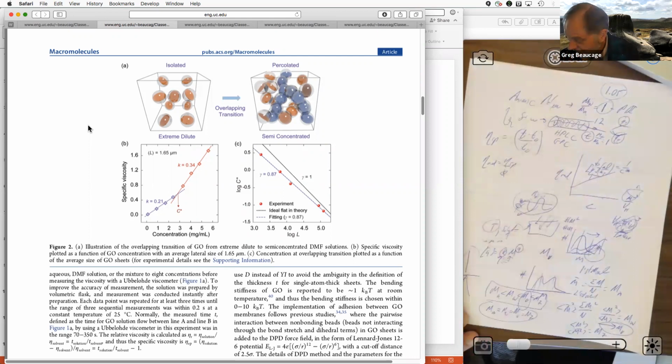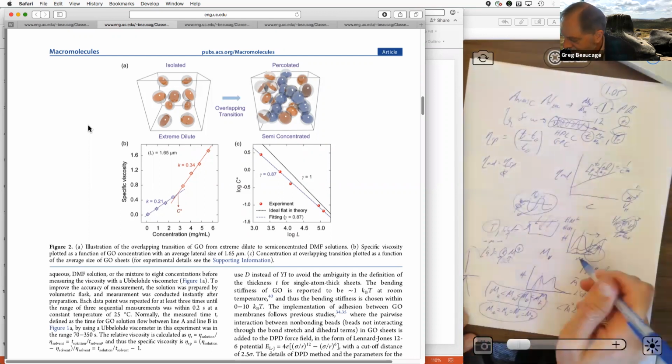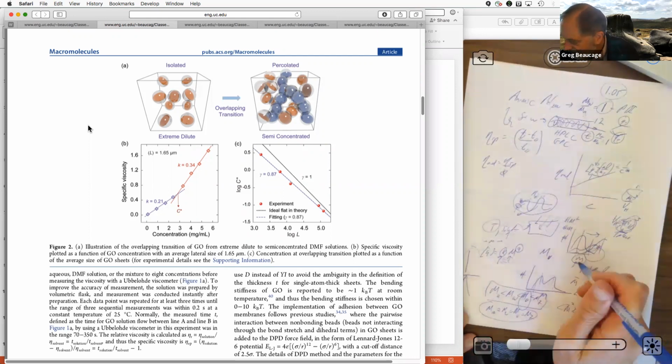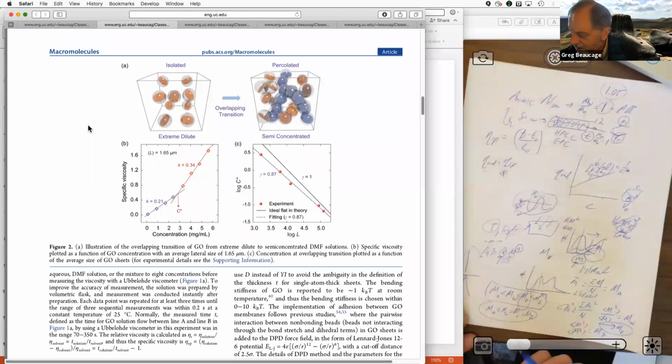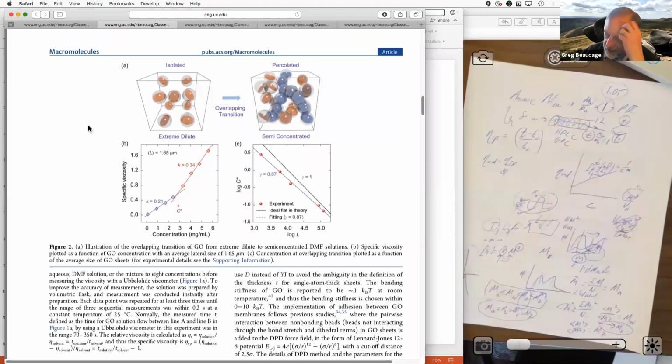Right. So on the scale, instead of time, you'd have this curve instead of time. You can swap it with molecular weight. So you have retention time versus concentration. You change this to molecular weight using the Mark-Houwink equation. If you had a viscometer attached to a GPC, that's the common thing that's going to be done in a lab.